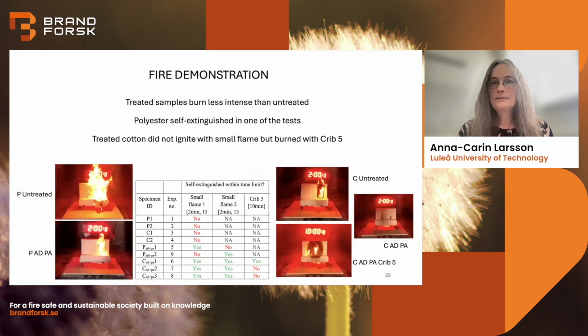We can summarize those results and see that for polyester, the treated sample burnt less intensely than the untreated, and the same for cotton. Untreated burnt more intensely than the treated one, which didn't burn at all, it just self-extinguished.